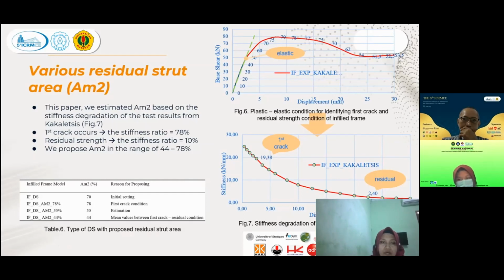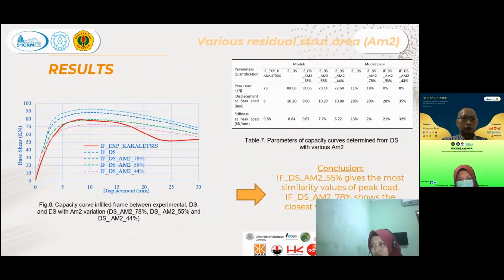We propose AM2 in the range of 44 until 78%. From this analysis, we can get the result that IF DS AM2 with 55% gives the most similar value of peak load, and IF DS AM2 with 78% shows the closest value of stiffness at peak load.